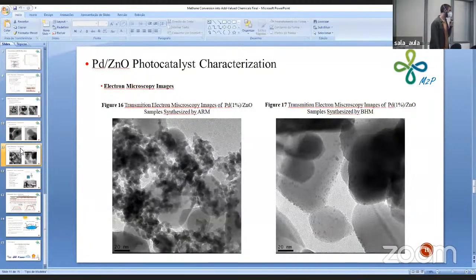Here we have some more images where we see with more clarity the difference in the agglomeration and the size of the particles. In the alcohol reduction method, we have particles in the size range of 4 to 5 nanometers, and in the borohydride samples, particles of 1.5 to 3 nanometers.